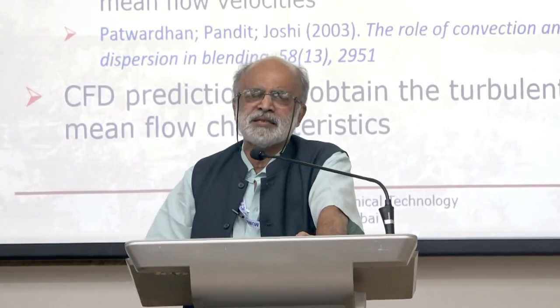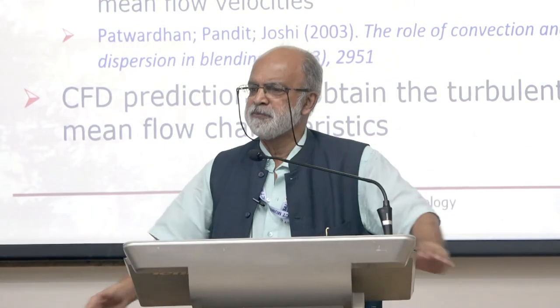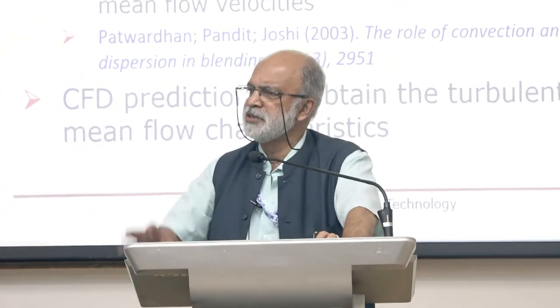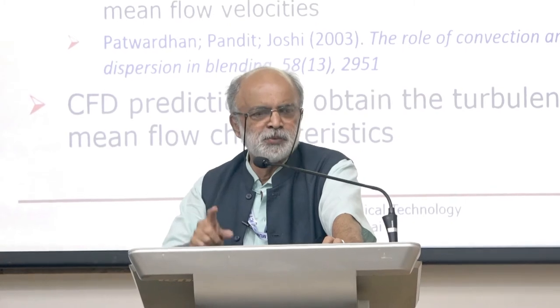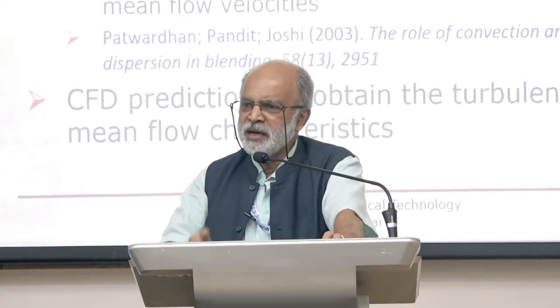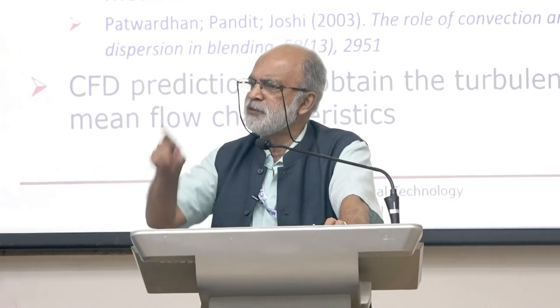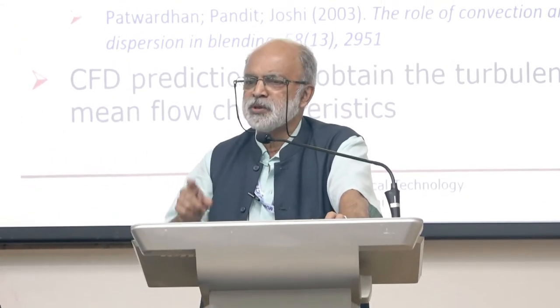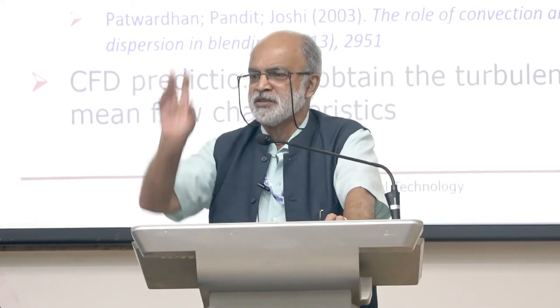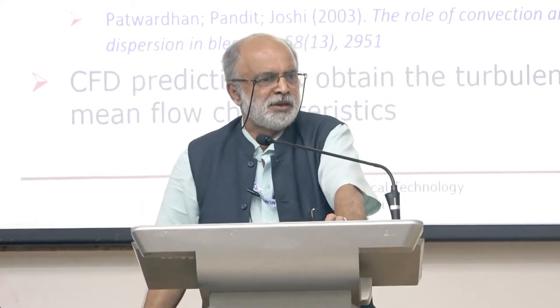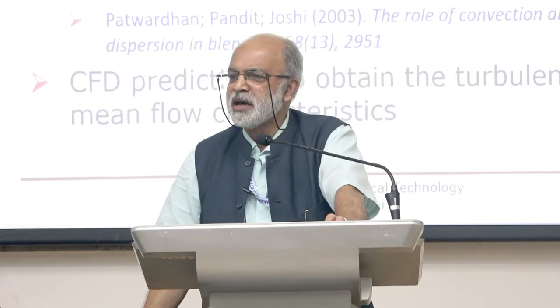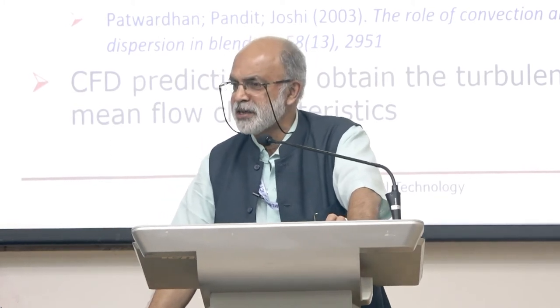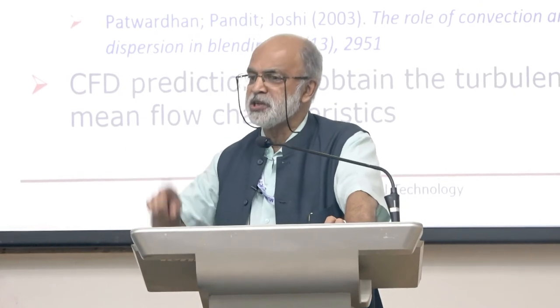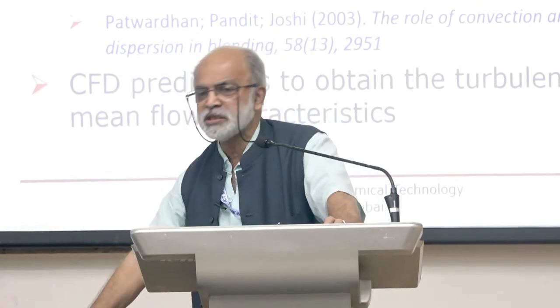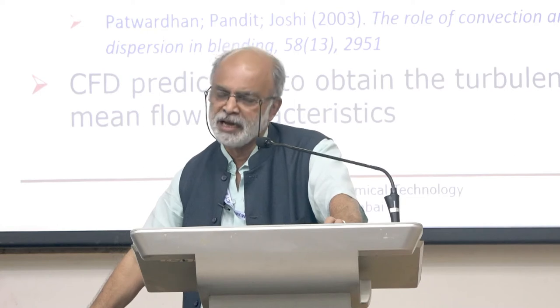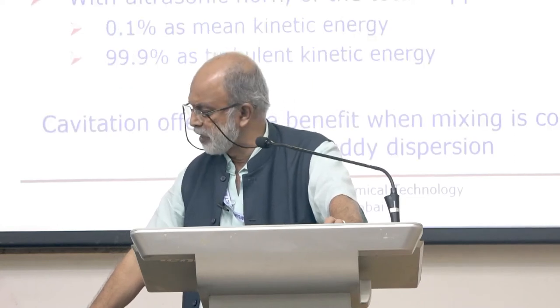And we did a very nice study. We took a 1 meter diameter tank and we put the same amount of energy, total quantum of energy put in the system remains the same, but in one case we put that energy in the form of a flow, in another case we put that energy only in the form of turbulence, and we came to a conclusion that turbulence alone is not sufficient. You require a combination of the two to get the best effect as far as mixing and dispersion is required. Of course, this can then be utilized using CFD. I'll give you some examples of that in due course of time.